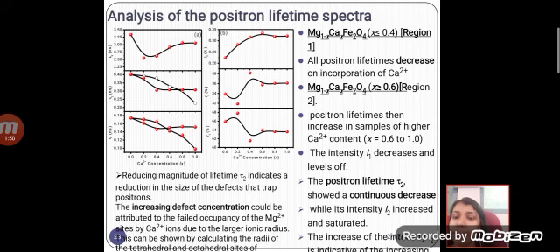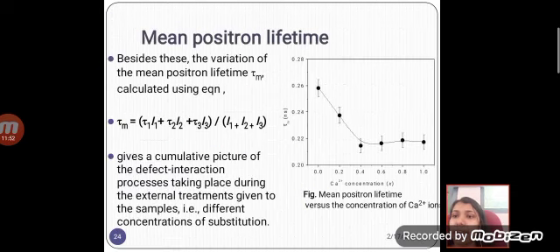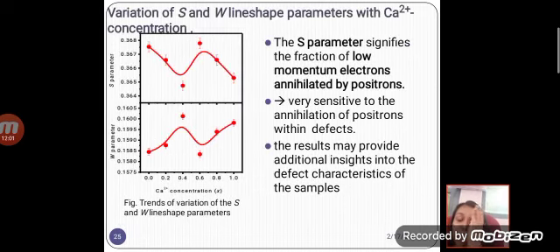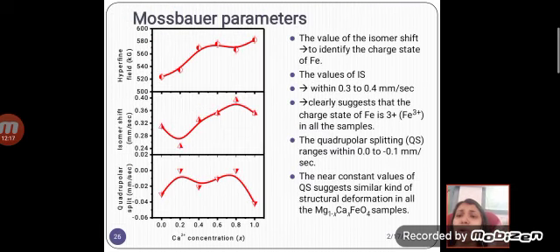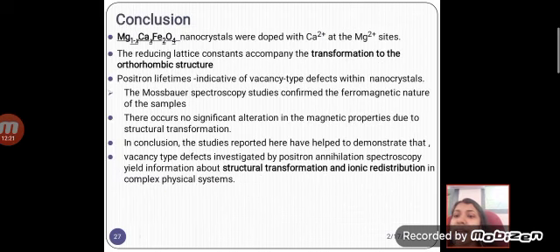We can see it plotted from the graph, and we have calculated the mean positron lifetime, which gives a cumulative picture of the defect interaction process taking place in the samples. And from the coincidence Doppler broadened spectra, we have calculated the S parameter and the W parameter, which is indicative of the low momentum electrons that get annihilated by the positrons. This is very sensitive to annihilation of positrons within the defects. And we can see the Mossbauer parameters, which suggest the ferromagnetic nature of the samples.